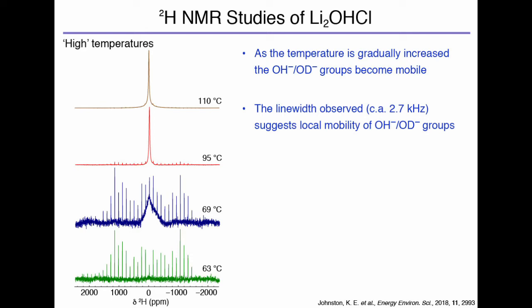There's no movement. When we increase that temperature further to 69, you'll see that we start to get something unusual happening. We have a sort of a broad peak here in the center, but we still have this manifold of bands around that broad peak. And then as we increase the temperature further to 95 and 110, the same thing happens, in that this broad thing that started at 69 becomes the dominant species.